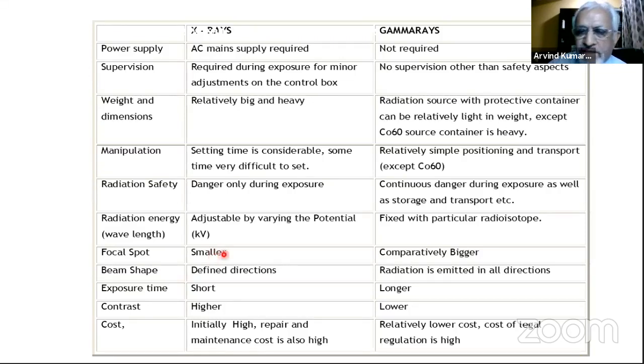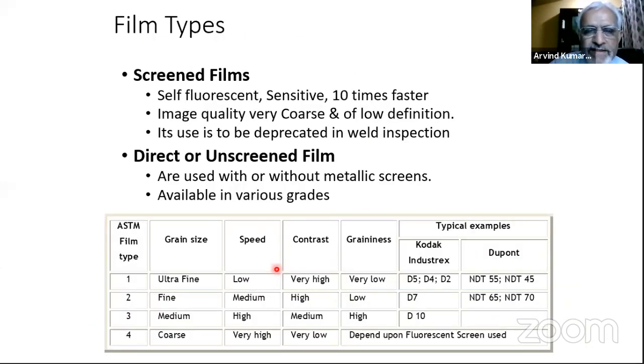So X-ray focal spot is small compared to the gamma radiography. That's why it is giving a good contrast and the other things. Other factor is the film. The type of film that you are going to use is going to make a difference about the final sensitivity that I am going to get.